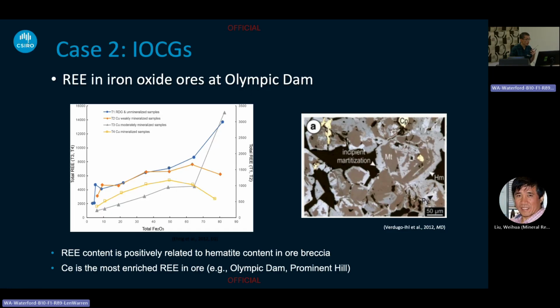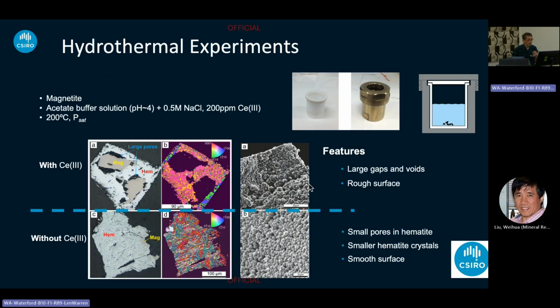Another thing we found is that the light rare earths are among the most enriched elements in the ore. The picture on the right shows the textures of magnetite being replaced by hematite. We don't understand why the rare earths are correlated with iron oxide, especially hematite. And not only rare earths, there's also copper and uranium in some deposits, and they are also related to this hematite replacing magnetite.